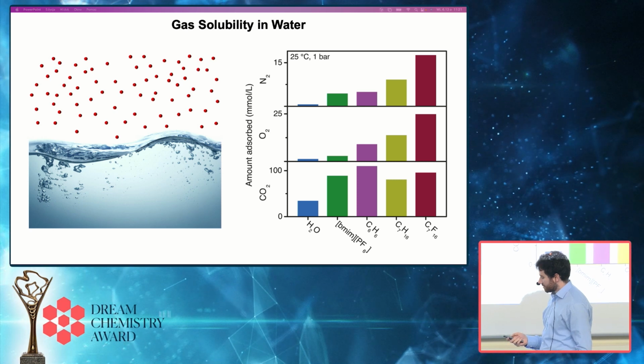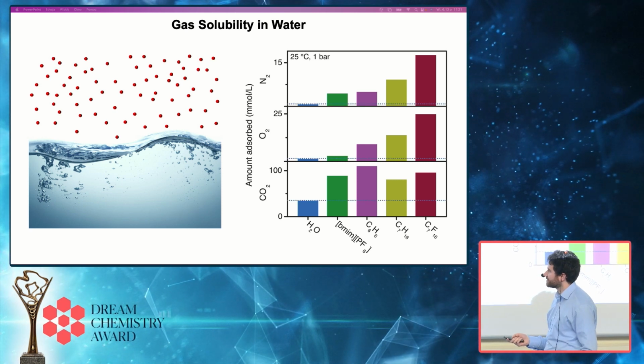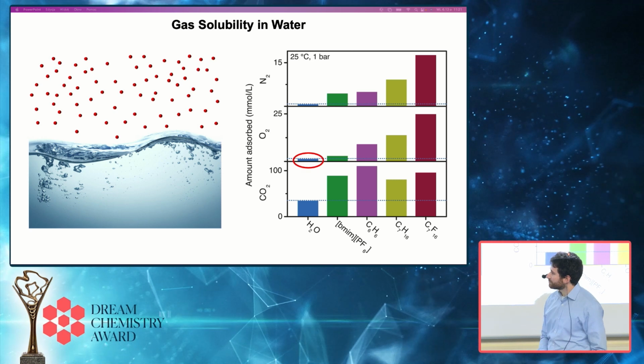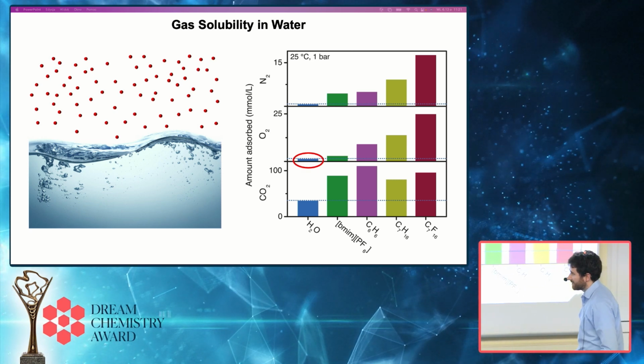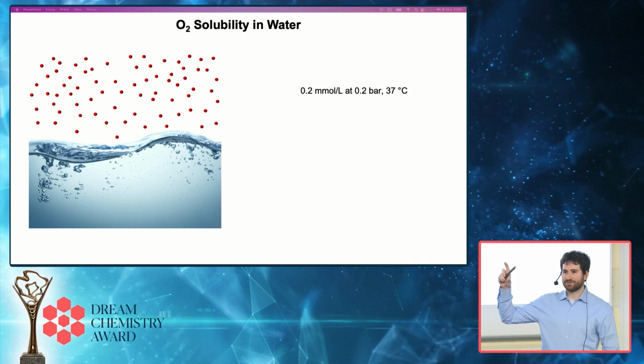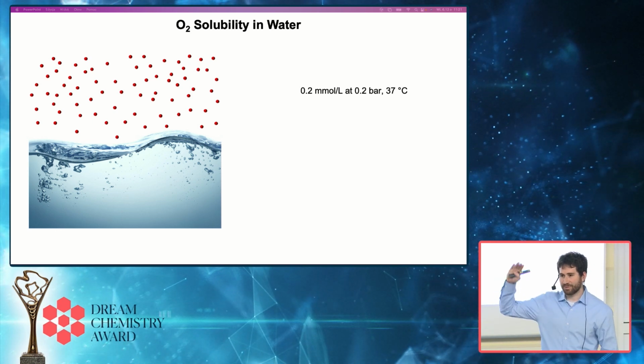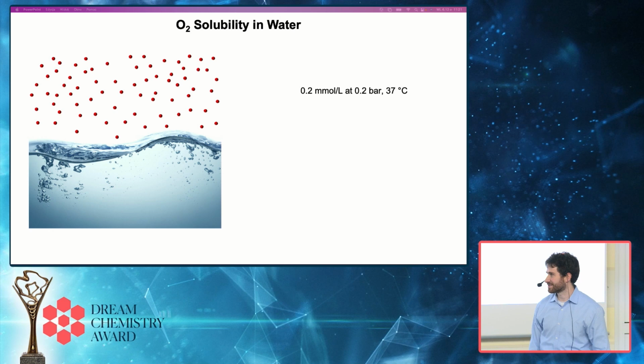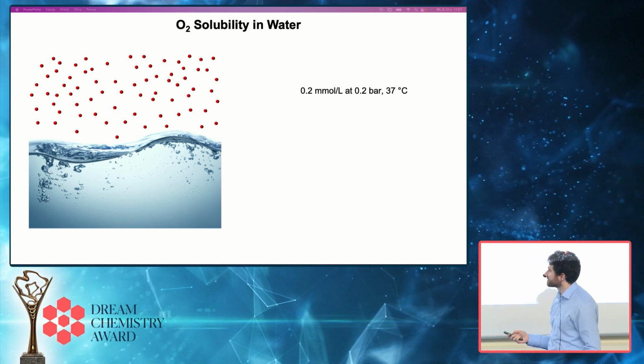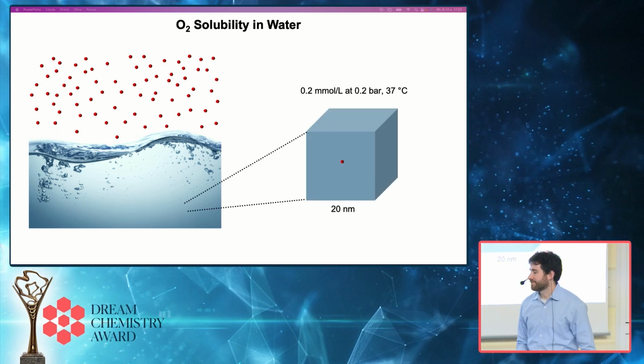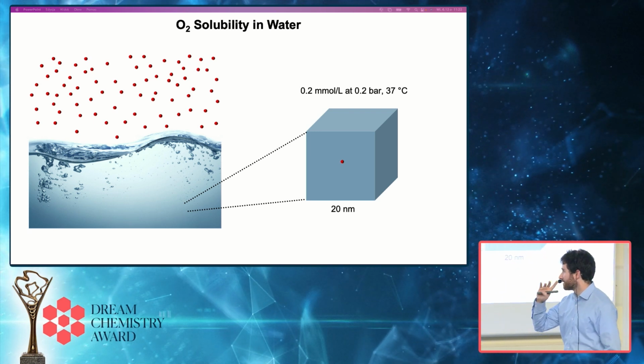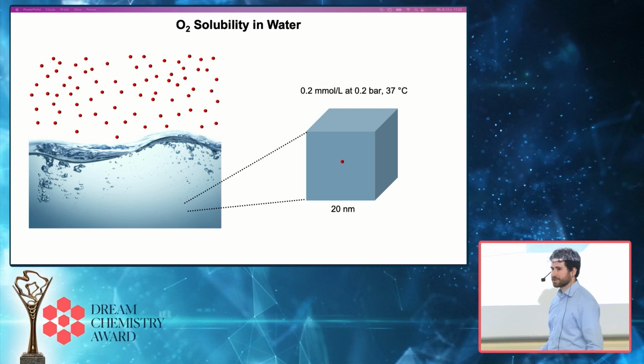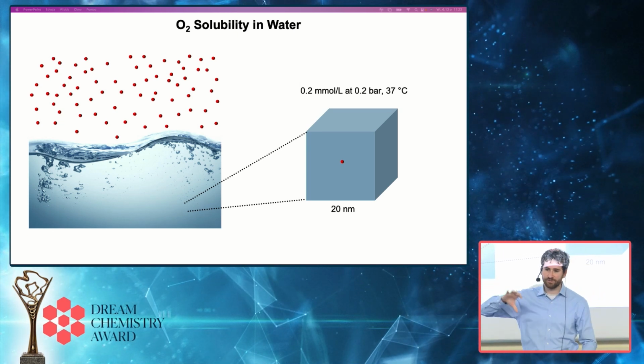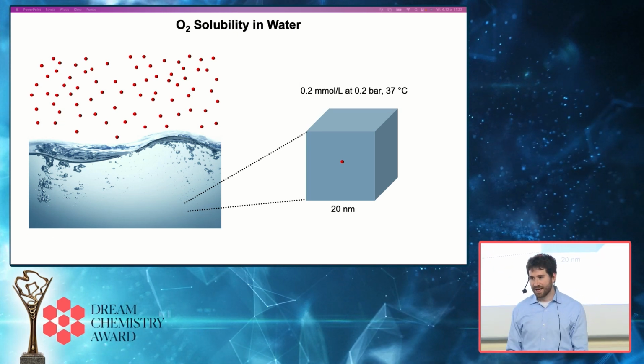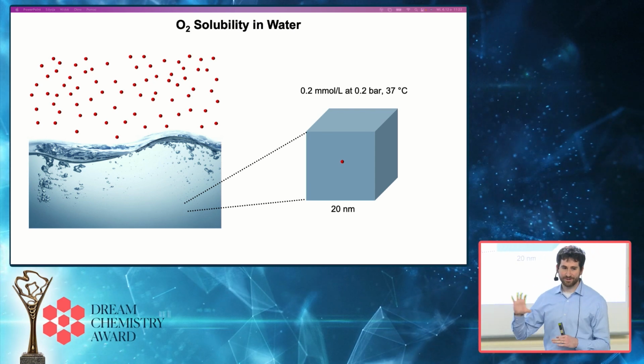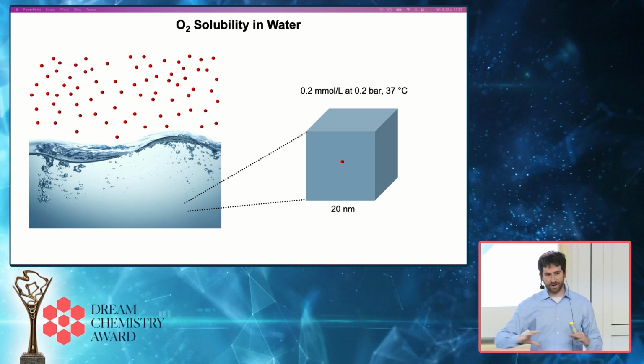You can really see this in particular in the solubility of oxygen in water, which is extremely low. Just to put this in context, if you think about a glass of water that's equilibrated with the air above it, so 0.2 bar partial pressure of oxygen in air under physiological conditions, so 37 degrees Celsius, the amount of oxygen that's dissolved in that water is about 0.2 millimolar, which corresponds to just a single oxygen molecule in every 8,000 cubic nanometers of space. So oxygen molecules in water under normal physiological conditions are very far apart, right?